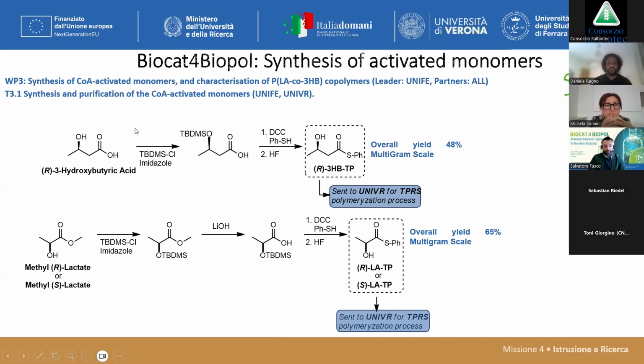This is protecting group chemistry that allows us, starting from 3-hydroxybutyric acid and from the methylic ester in both enantiomer configurations of lactic acid, to synthesize activated monomers, activated as thioesters. These thioesters are the ones that Salvatore, at the University of Verona, uses for the transesterase reaction.